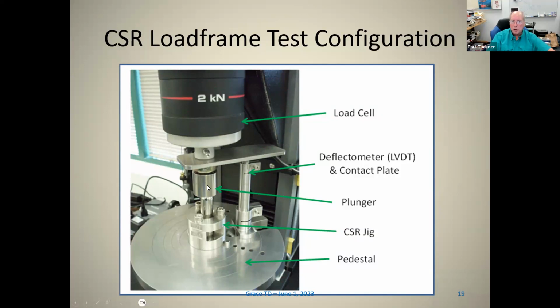Then there's a plunger here, which is a small cylindrical thing that's hardened that runs up against the indenter pin that allows you to do the deflection. And then there's a pedestal, which is hardened and locking, just like the plunger is, so you don't have any slack in the system. And then there's centering pins that allow you to slide the jig right up against the centering pin that ensures you're on center. So it makes it easy to do the test, and it's a really nice test configuration.